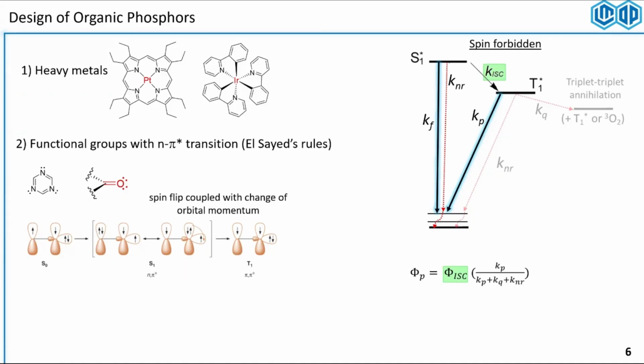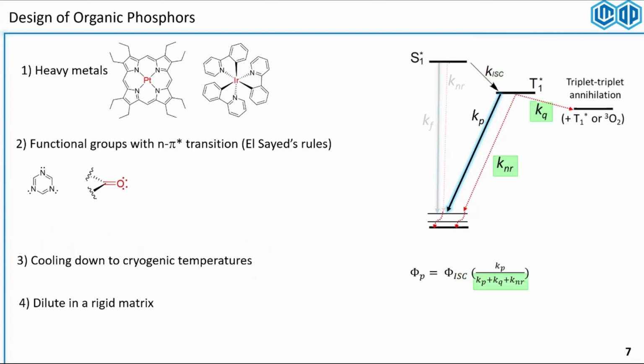And to enhance the intersystem crossing rates, we either need to embed heavy metals inside, normally iridium, platinum, or add functional groups with n to pi star moieties to enhance this intersystem crossing through a change of orbital momentum and generate these triplets. Once the triplets are generated, then we have to preserve them from all sorts of different pathways that could decay and not allow any phosphorescence emission for us.